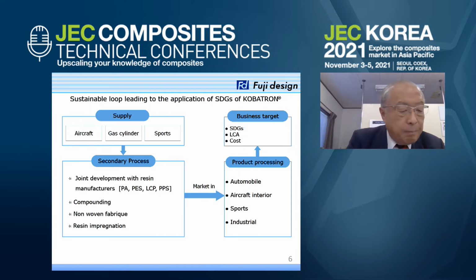In recycling pyrolysis, we select several thermal heating programs according to the material condition and thickness. If the thickness is thicker, we can elongate some temperature area to elongate the treatment time to get the same RCF property for compounding or non-woven fabric preparation. For compounding RCF, residual carbon content is controlled at 3 to 5%. For non-woven fabric, residual carbon content is controlled lower than this value.